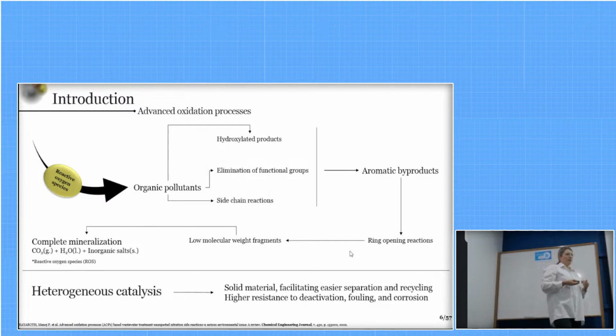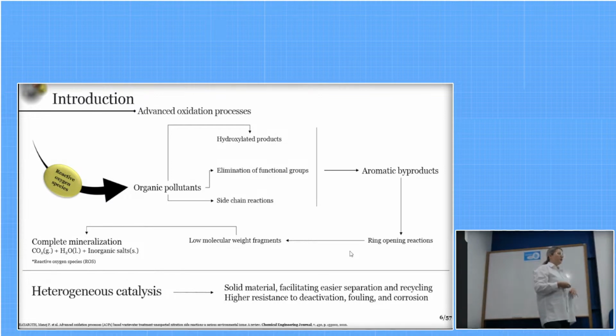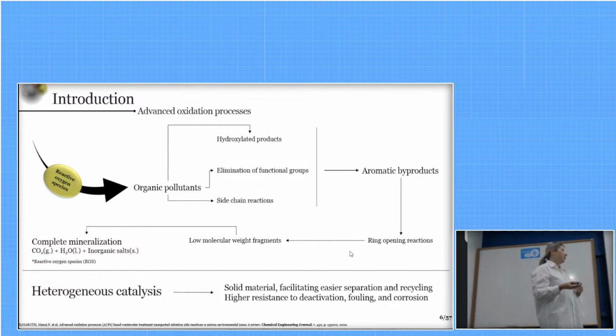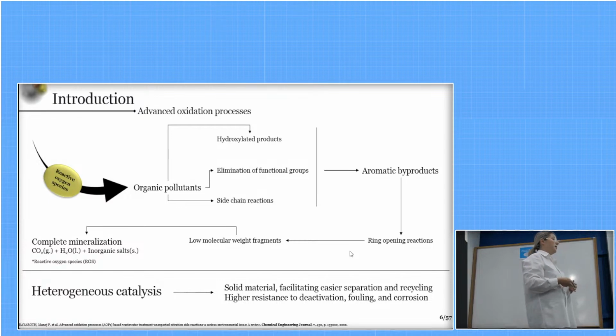The advantages of using microwave in the systems is promoting rapid and uniform heating, the formation of hot spots, which are spots with much higher temperatures than in the bulk solution, and synergic effects due to the electric field and the magnetic field passing through the sample. As any other process, the use of microwaves imposes challenges, and the challenge here is designing catalysts specific for microwave-assisted applications. So the catalyst needs to be able to produce hotspots and reactive oxygen species simultaneously, while keeping structural stability, because when we work with microwaves, we are working under high temperature ranges.